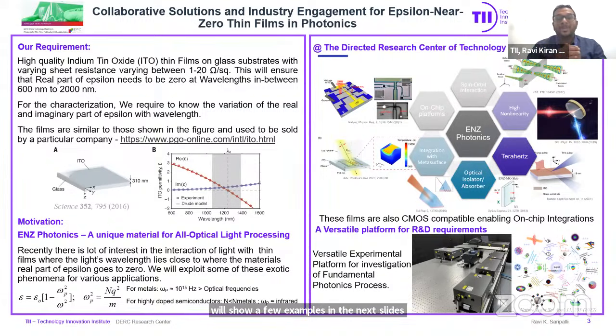And this plasmon frequency itself depends on the number of charge carriers and what kind of charge carriers we have. And this is why we need highly doped semiconductors, such as indium tin oxide or aluminum zinc oxide, for that matter. And this is a particular example in the figure, where this is a film with 300 nanometers thickness of indium tin oxide on a glass substrate. And when you do a reflectivity and transmittivity study, we see that the real part of epsilon comes to 0 at around an infrared wavelength, which we can access in a photonics lab.